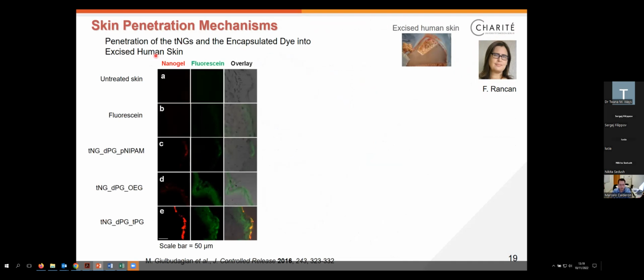And what we could see here, when we have our nanogel fluorescently labeled, and I just took this image to make the analysis simple, is that our nanogels mostly accumulate on the outermost part of the skin, so in the stratum corneum, on this layer of dead cells. And then when we see how the cargo molecule penetrates, we could see that the cargo molecule actually goes beyond this stratum corneum, and it could penetrate into the first layers of the viable epidermis. But we could also very nicely see that it penetrates into the dermis, which in most cases is very, very difficult.